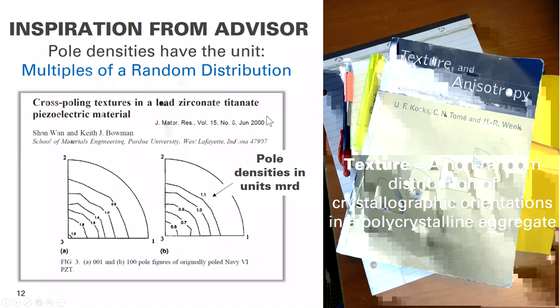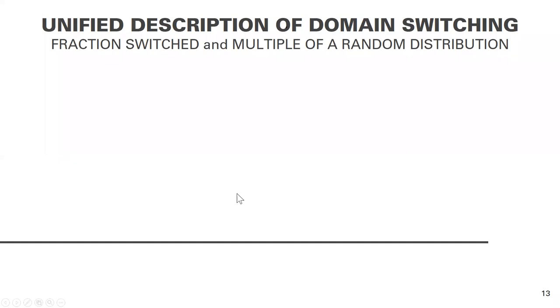And so he had published a couple papers on this earlier, this one, for example, from 2000, where they actually measured full pole figures for textures, both from poling and cross-poling in the tetragonal PZT. And so what you see on these pole figures is you see numbers that represent the pole densities in this unit multiple of a random distribution, again describing the degree to which the domains have reoriented. Okay. Now, what I did early on as a graduate student is I tried to marry these two concepts. And so we ended up publishing my first paper on this topic, which I believe is really a unified description of domain switching. So we take this idea that we can describe these switched volume fractions and also describe it as a multiple of a random distribution.